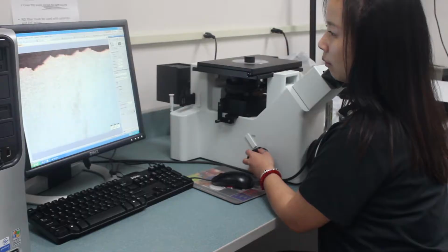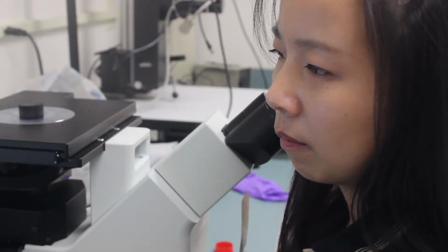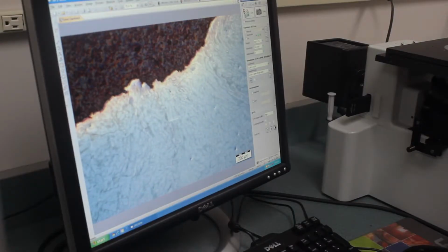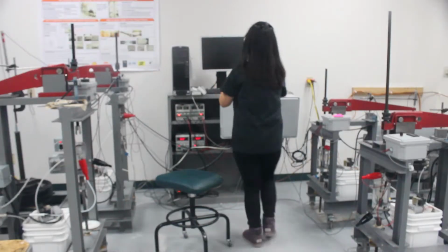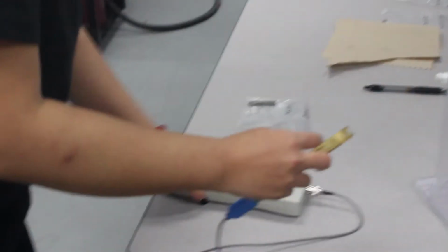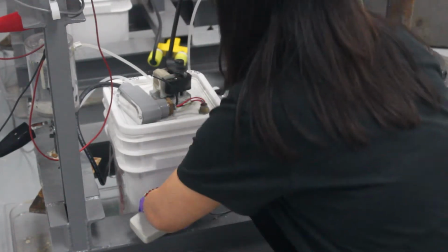According to the ASTM standard E562, the point counting method was used to analyze the ferrite content with the images taken from an optical microscope under the magnification of 200x. Before testing the welded samples to rank the susceptibility to hydrogen-assisted cracking by the time to fail, tests on simulated heat affected zone samples were conducted first.